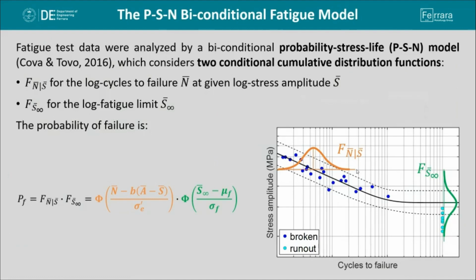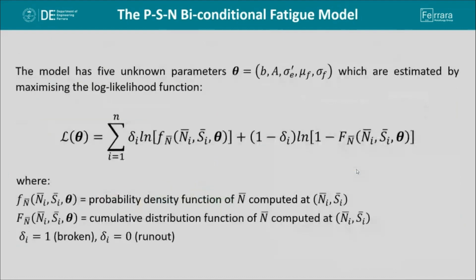In this case, the first distribution function, the orange one, is related to the log cycles to failure at a given log stress amplitude, while the second distribution function is related to the logarithm of the fatigue limit. Finally, we can say that the probability of failure of a fatigue specimen is the product of the two distinct distributions. In order to make it work, the model has 5 unknown parameters, which are estimated by maximizing the log-likelihood function included in the present slide.